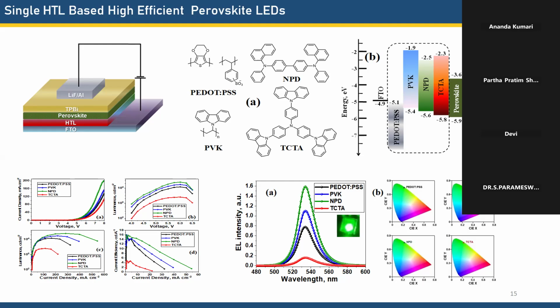Then you can see the EL intensity in the bottom middle one, the EL intensity versus the voltage. You can see a very nice comparison of the EL spectra. The green color is the NPD based device, that is the champion device, compared to the PVK in blue, PEDOT:PSS in black, and TCTA in red. In this study, with the electroluminescence intensity, we got a 533 nanometer good green wavelength peak, and the highest champion device is the NPD based device. Inside you can see the green light also.